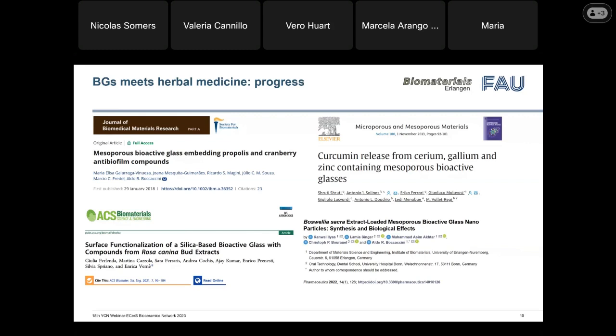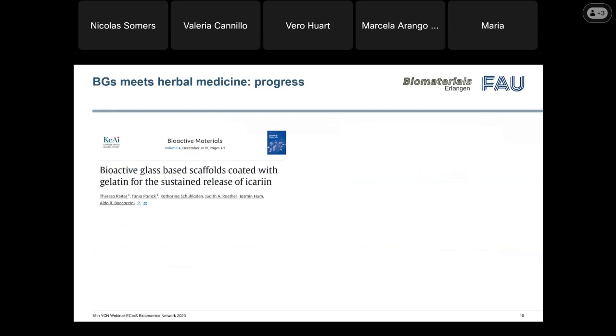So depending on the concentration of the compound, they had higher or lower activity, but this is quite expected for either ions or herbal medicine compounds, sorry. Moreover, the use of icariin has been quite studied as well, but in this case on bioactive glass scaffolds, and here a polymer was used as the carrier of the drug. They worked a lot on the optimization of this polymer for the release of the icariin, for example, cross-linking the gelatin and so on, so that the coating was not degraded quickly.